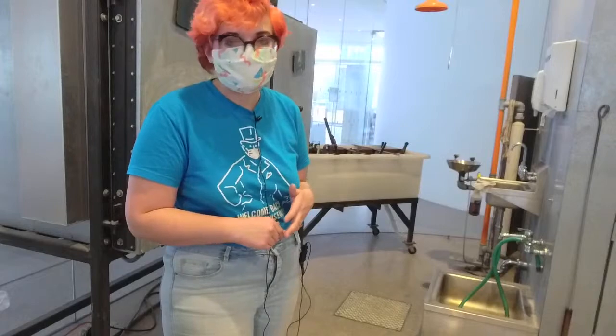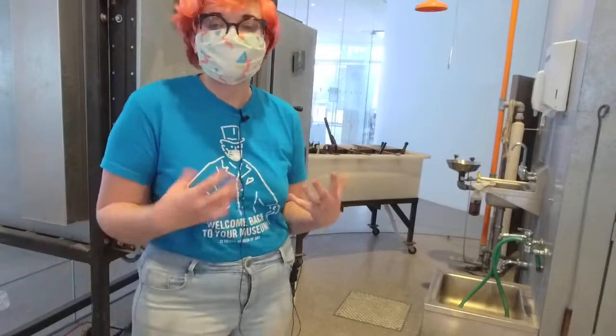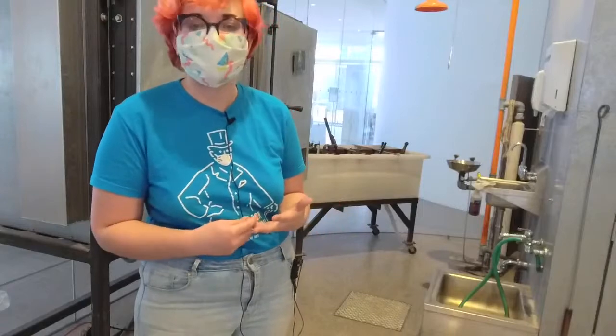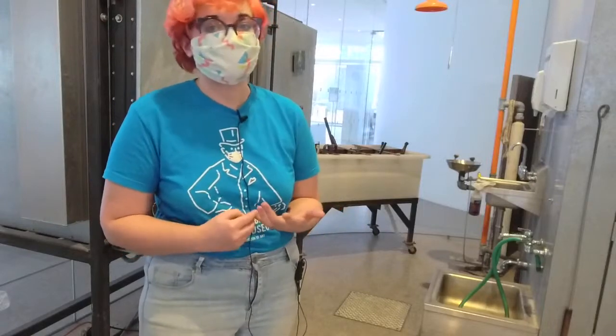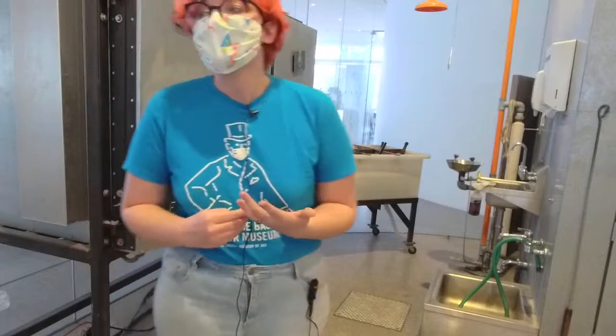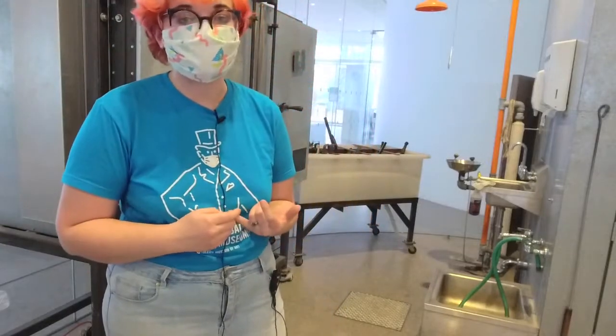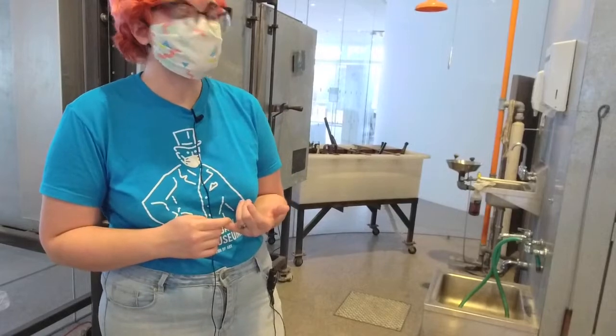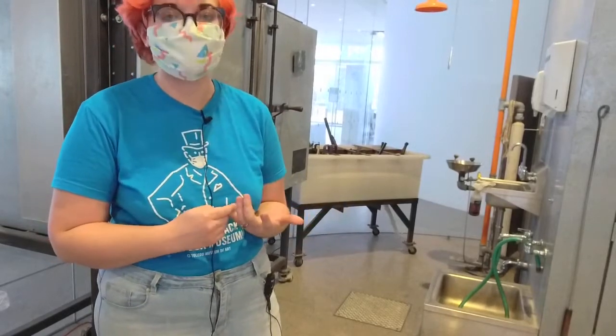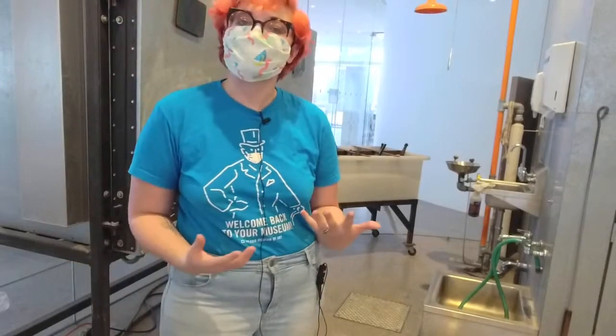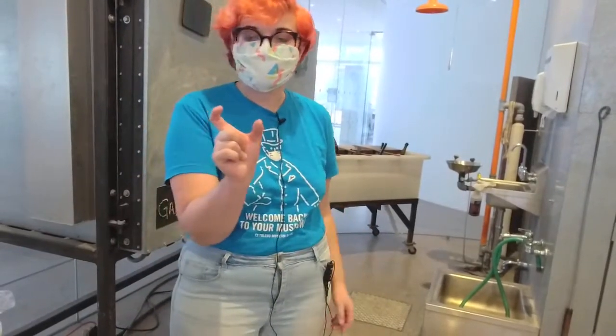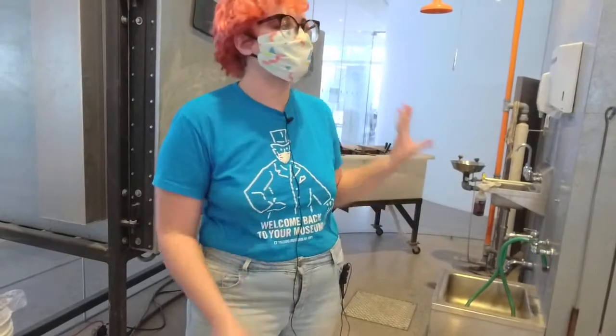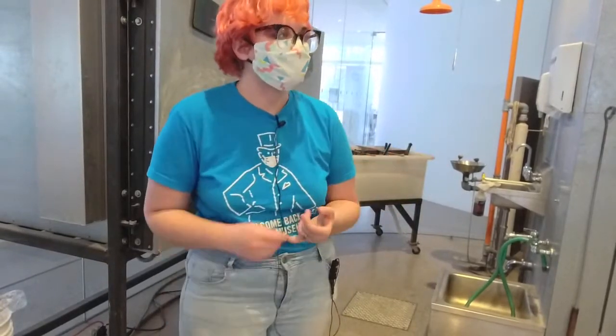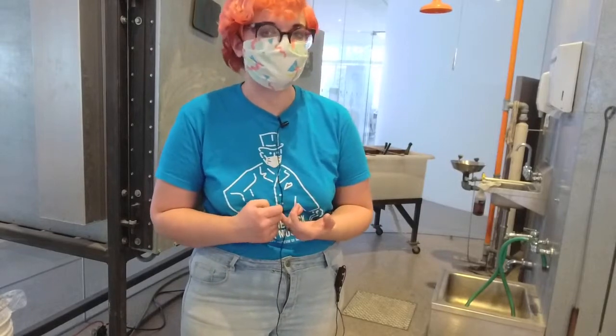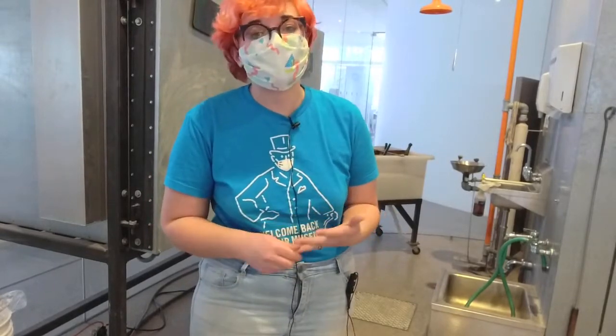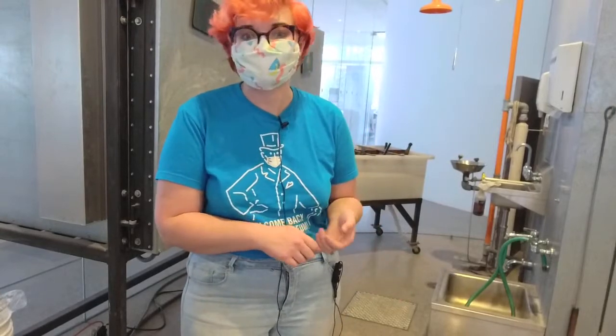Another thing about annealing is that the bigger or thicker something is, the longer it will take to anneal. So if you do come into our galleries, we have a cast dress from Katie Lamont, and that took around 6 months to fully anneal. The reason is that it's around 2 to 3 inches thick, whereas everything we're making today has a maximum thickness of about 1/2 inch. So even though it feels really heavy, it's thin all the way through, so we can anneal really fast.